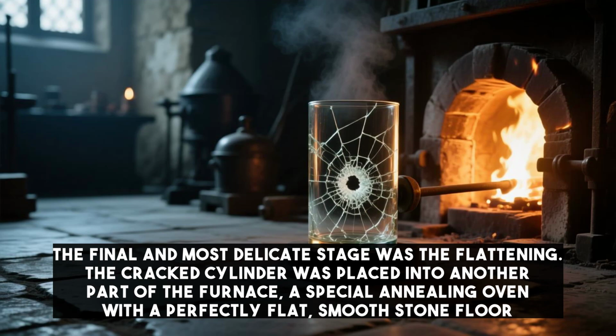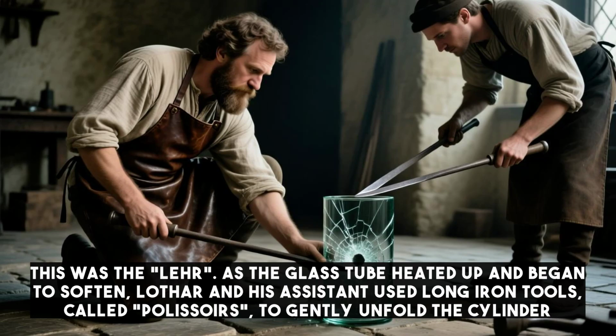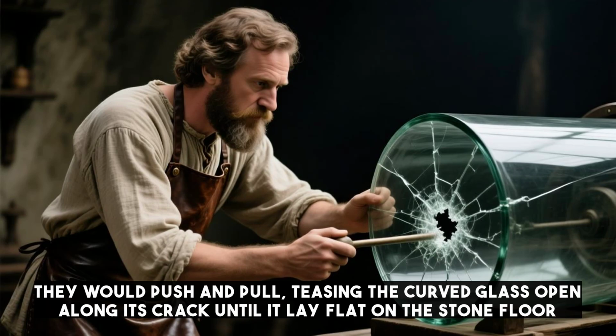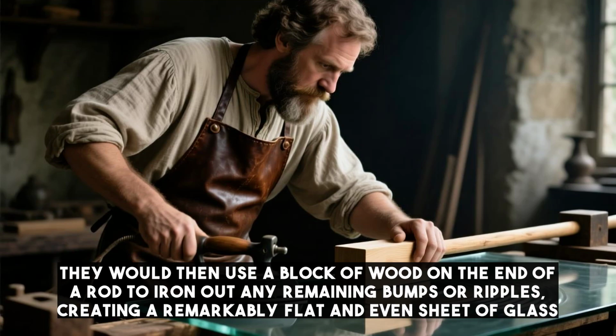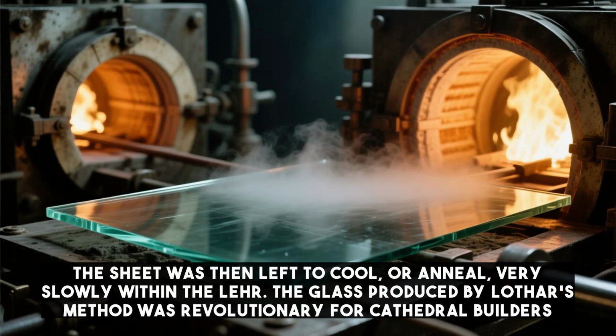The final and most delicate stage was the flattening. The cracked cylinder was placed into another part of the furnace, a special annealing oven with a perfectly flat, smooth stone floor. This was the lehr. As the glass tube heated up and began to soften, Lothar and his assistant used long iron tools called polissoirs to gently unfold the cylinder. They would push and pull, teasing the curved glass open along its crack until it lay flat on the stone floor. They would then use a block of wood on the end of a rod to iron out any remaining bumps or ripples, creating a remarkably flat and even sheet of glass. The sheet was then left to cool, or anneal, very slowly within the lehr.